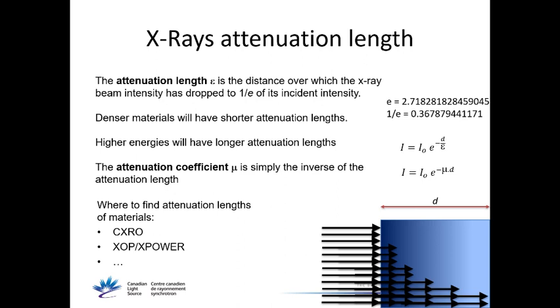This penetration depth is characterized by the attenuation length, often denoted ε, where μ is just the inverse of the attenuation length. The attenuation length is a characteristic length that is important to know when you are going to characterize thin-films. There are tables where you can find them for different materials depending on the atoms present and how densely packed they are.